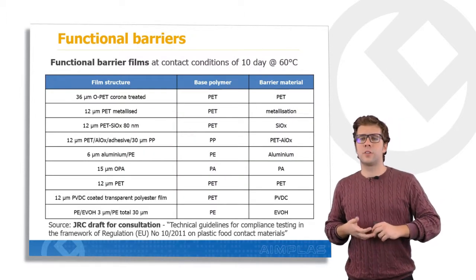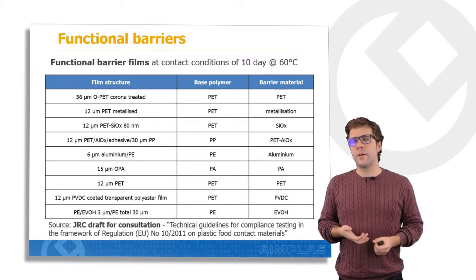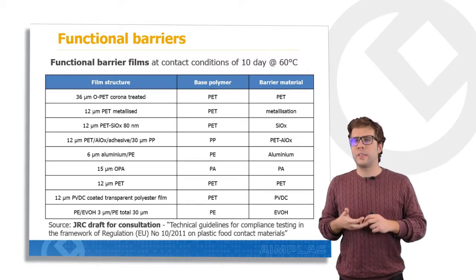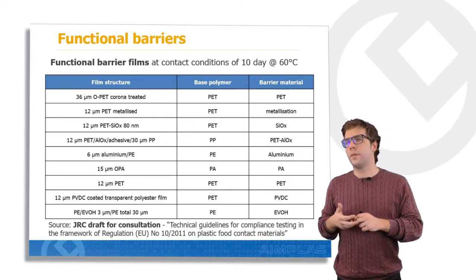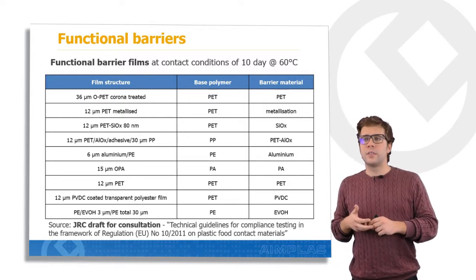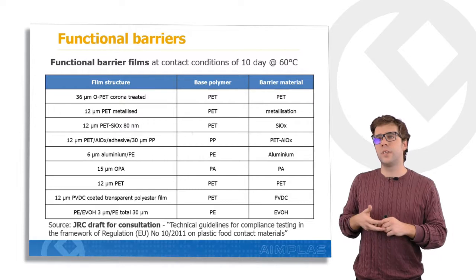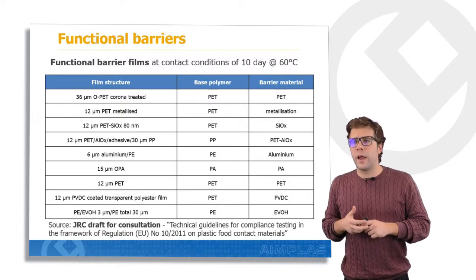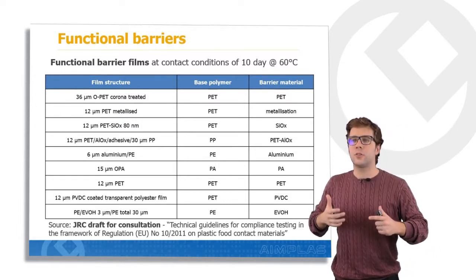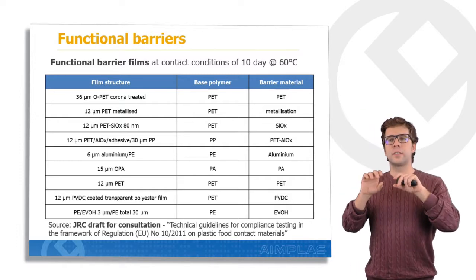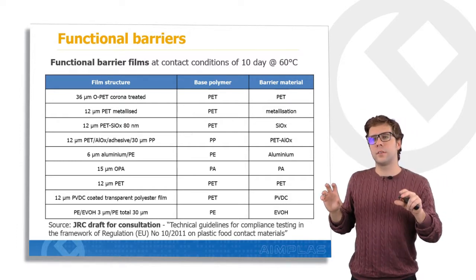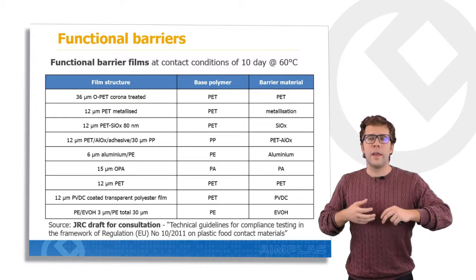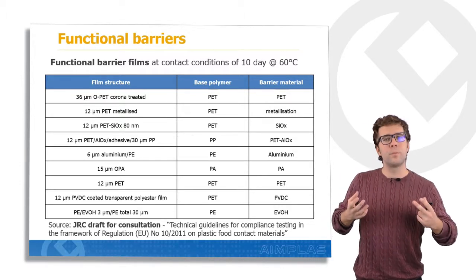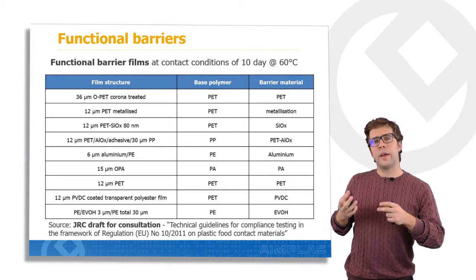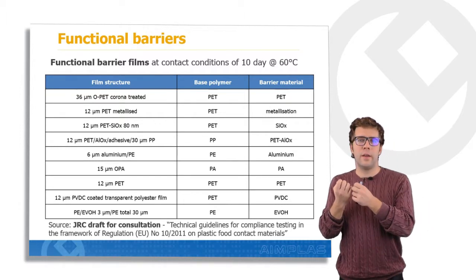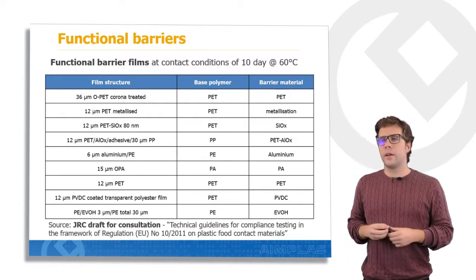And we also have some examples of functional barrier films, in this case at contact conditions of 10 days at 60 degrees Celsius. And what we can see here is that not only polymers can be used as functional layers, but also different types of coatings could perform this functional barrier function also.